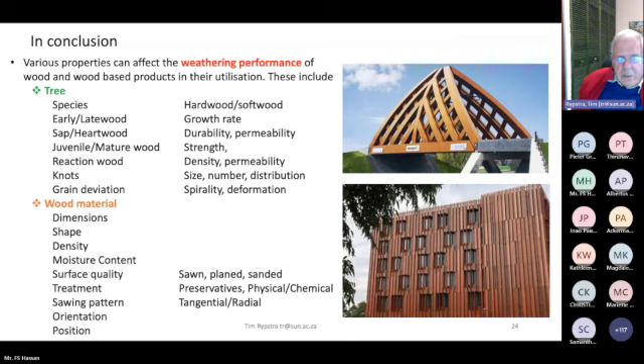Reaction wood, which is, all these tests are normally run on normal wood, but in reaction wood your density and permeability is affected. We normally work without knots when we do certain tests, because the introduction of knots, it just makes things more difficult. So, but the size, number and distribution of knots in woody material being exposed has an effect on its weatherability, and then grain deviations, spirality and deformation. So these are typically growth related influences that one tries to eliminate when you are busy with certain testing.